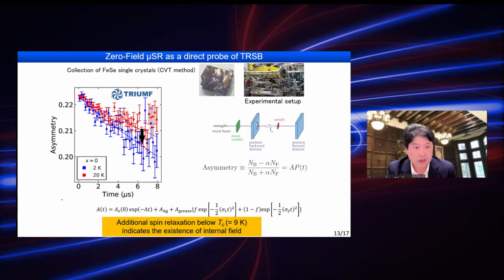We first look at iron selenide, using the collection of single crystals. Here is a plot of the μSR asymmetry as a function of time. You can see the relaxation.